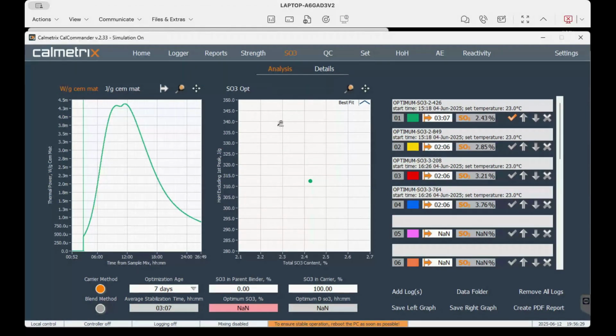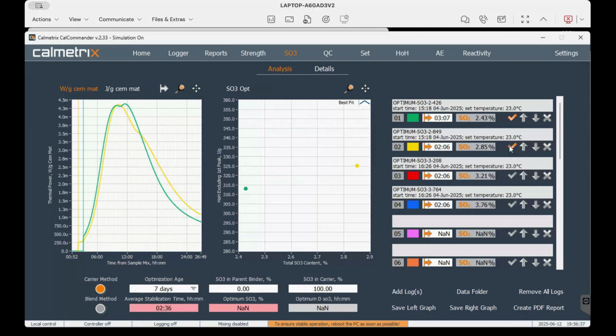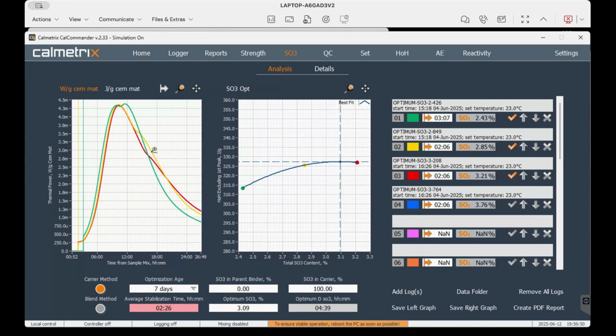Here you see, as you add more sulfate gradually, starting with 2.43 percent SO3, it gives you this. When you add a little more, you see that bump move to the right. So that sulfate depletion is quite a lot after the main peak, which is fine. Here it moved even further, you can see it here now. And as you add more and more, here you don't see it anymore.